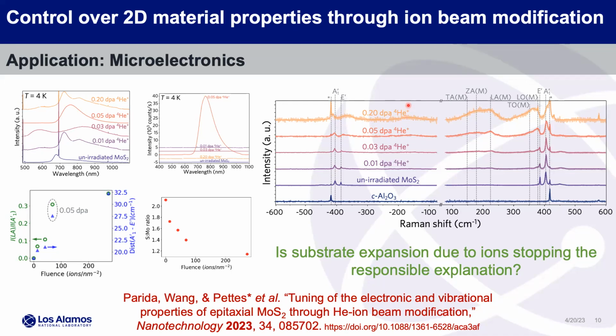DPA is displacement per atom. 0.2 gets pretty high; it correlates to defect densities of about 10 to the 13 or so. But what we saw is there's some synergy, because there's a really high emission at a certain value of DPA. This is 0.05 DPA. If we plot it in terms of the fluence, and plot the change in the Raman intensity of the longitudinal acoustic mode, which shows up because you have defects. It's not an optical mode, it's just a longitudinal acoustic plus a defect that gives you a Raman peak, next to the A1g, which is the out of plane Raman mode.